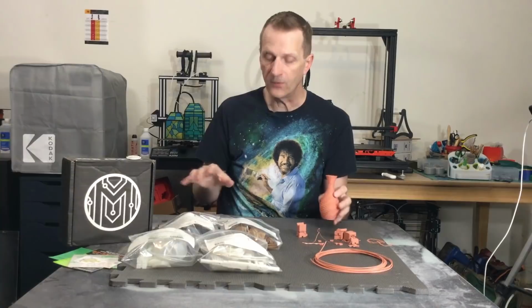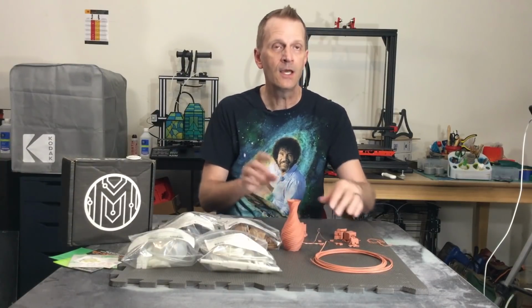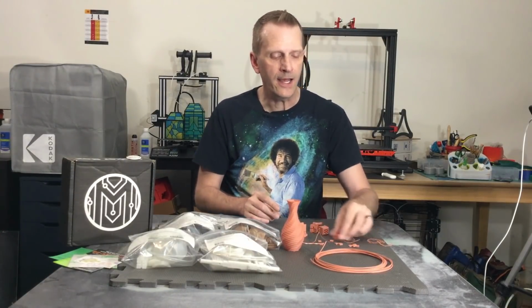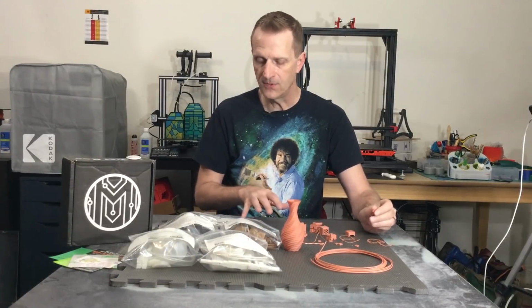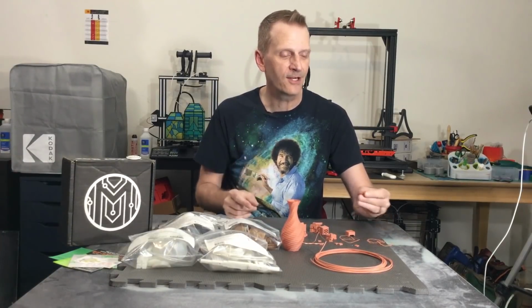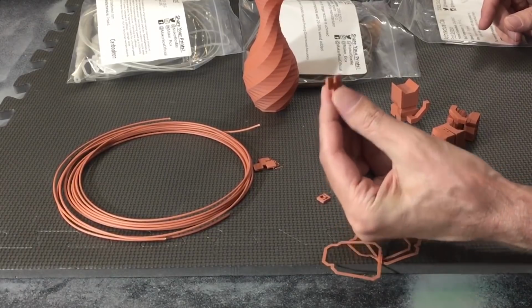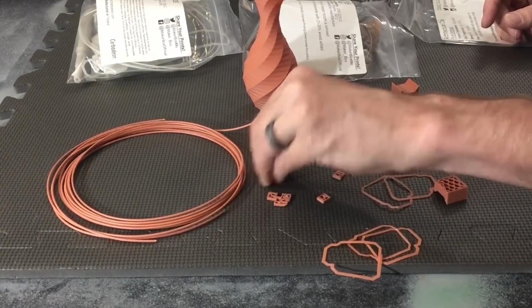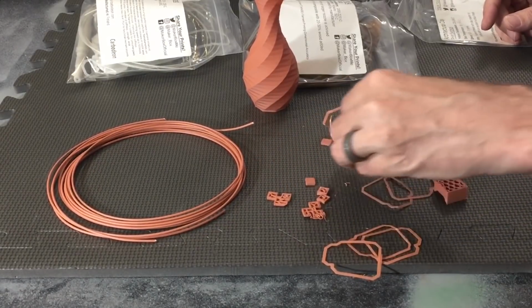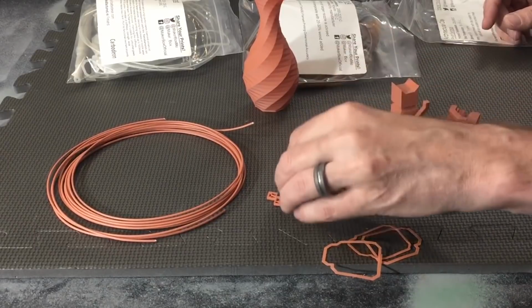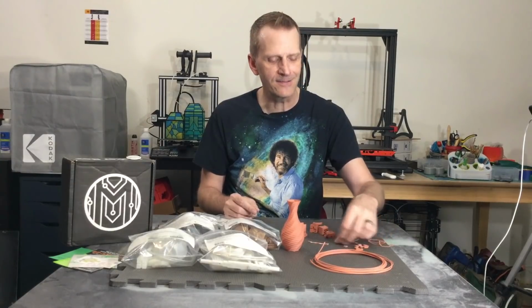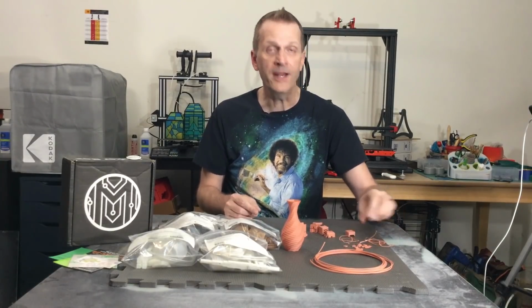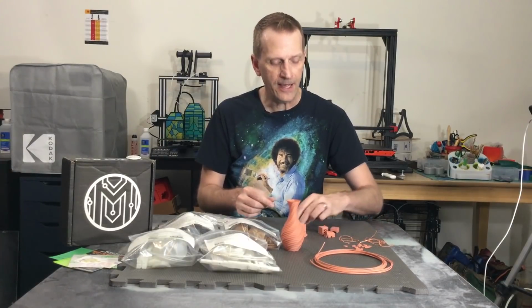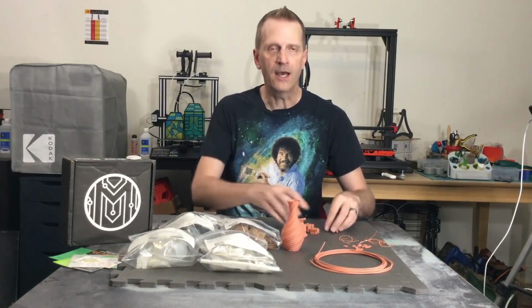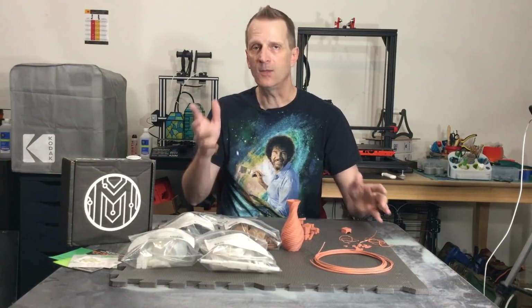So from the information here, we started with 220 C on the sanded acrylic bed. And right off the bat, I wasn't using the heated bed because I trust in that sanded acrylic. And of course, they didn't stick. They warped and came right off the print bed pretty quickly. I didn't get past more than a few layers before they were stuck to the hot end. So after 2 or 3 tries of that, because I'm a glutton for punishment, I went ahead and pulled the acrylic back off again, and we installed the glass bed with the heat and the Buildtak.